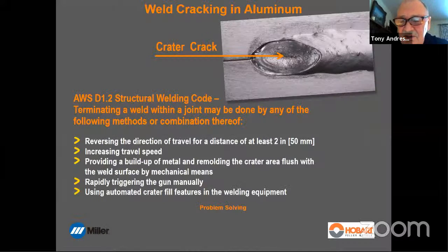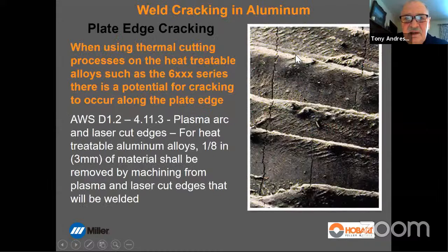Crater cracking, aluminum. You've got to be really careful about buttoning up those craters. You've got to fill in those craters, otherwise you're going to get crater cracking. This is an odd one that a lot of people have never seen. If you are plasma cutting any of the 6000 series or any of the heat treatable alloys for that matter, the codes require that you remove 1/8 of an inch of that prep before you incorporate it in the weld, because you're going to get these micro cracks across the surface of the weld.